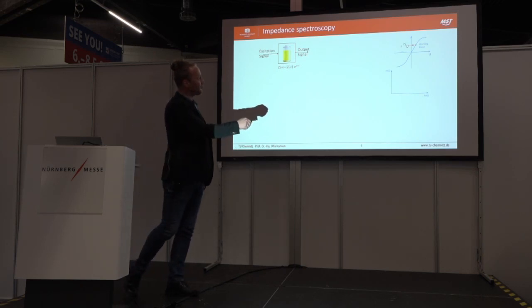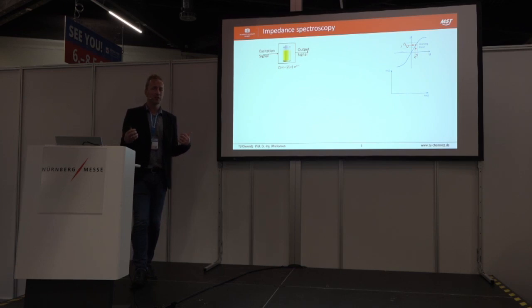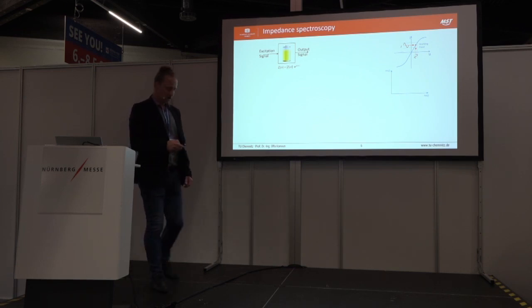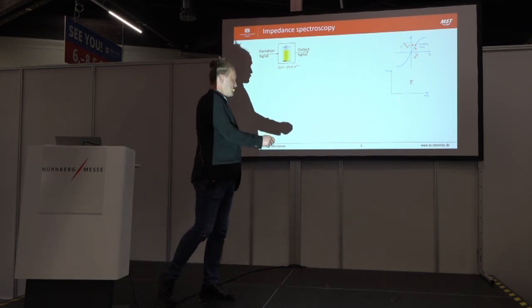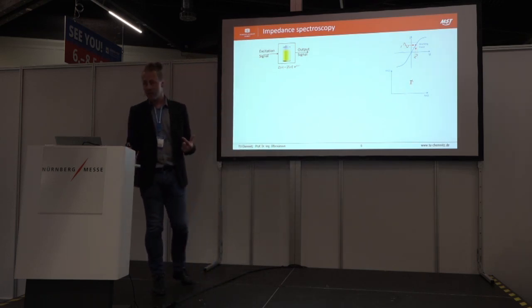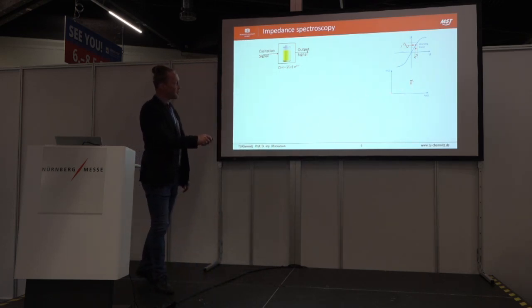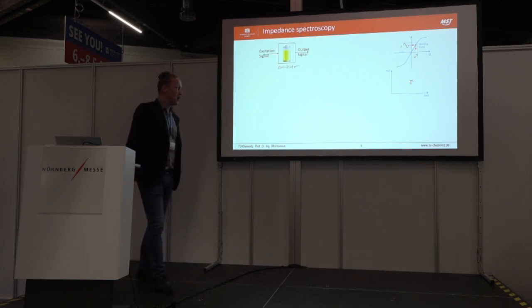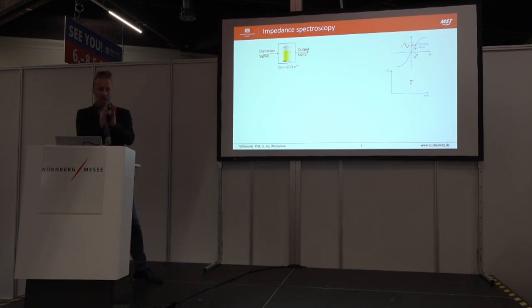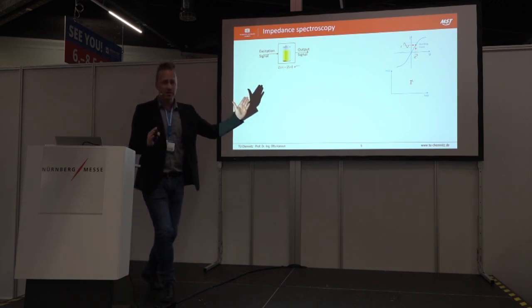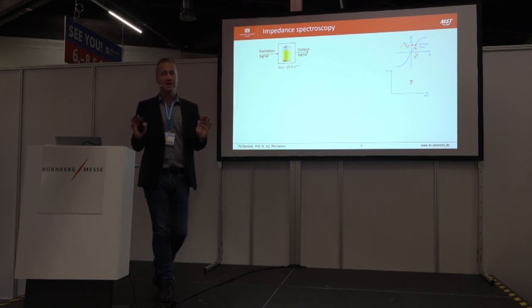Here in the IU curve, you see the excitation signal applied in a certain working point, a state of charge from this battery, and you get a corresponding response, a reaction from your system. This reaction you can calculate to one point in the Nyquist diagram. You see the real part and the imaginary part of impedance, and this is at the end one frequency measurement, and this describes almost the state of the art of impedimetric sensors.